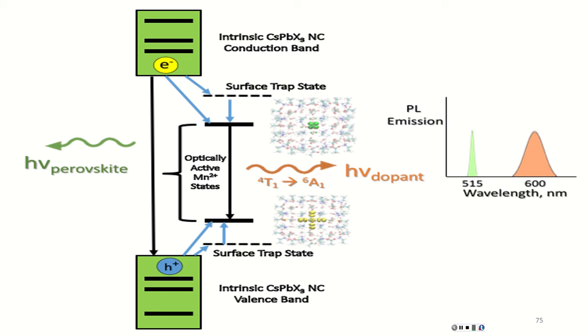If one would dope the quantum dot with a transition metal, which experiences splitting due to the crystal field in this bromine environment, the crystal field for this specific doping is smaller than the gap of the parent structure. And because of accumulation of several factors, the selection rules become favorable for making the transition between these split states optically active. And then this optically active state becomes independent of what is going on at the surface. So it will become a very stable emitter with or without ligands. So you just excite and observe emission. It is an original idea. And you see orbitals, occupied and unoccupied, are localized only on the doping atom.